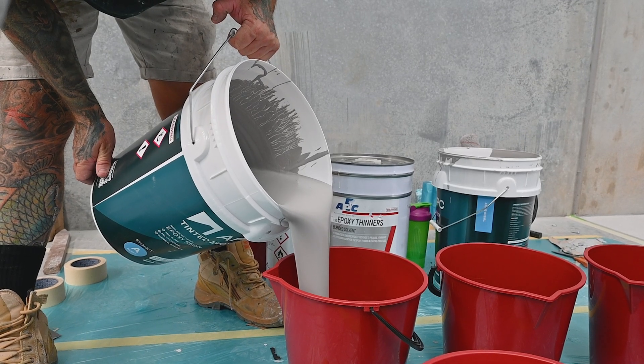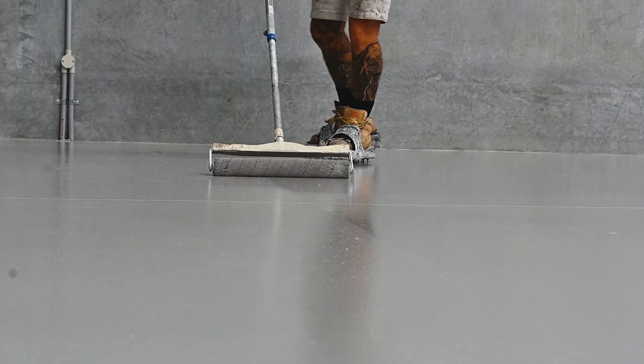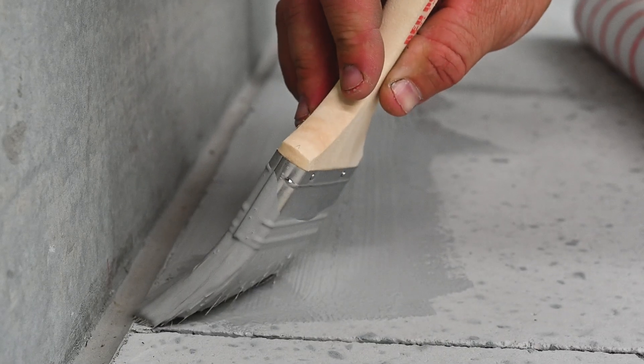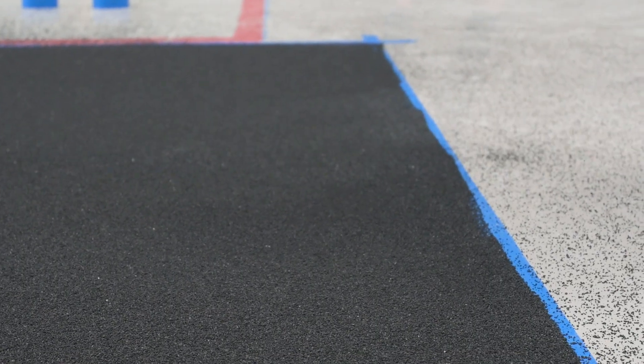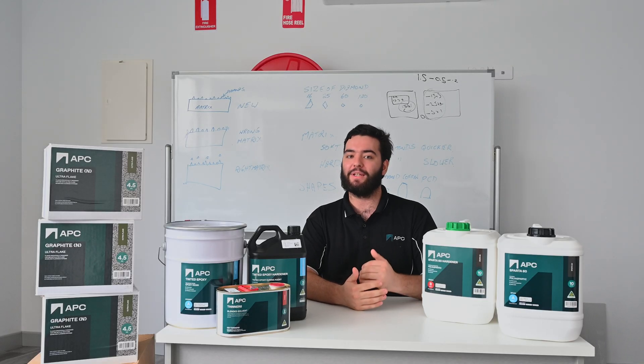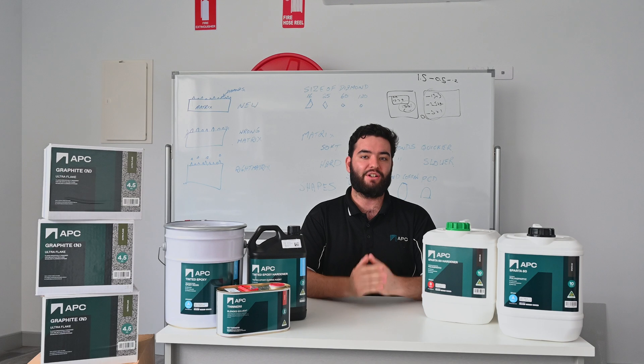These risks can be avoided by using our four-coat systems, which gives time for the product to penetrate into the substrate for a stronger bond. All of our systems begin with a prime coat designed to ensure a strong bite to the concrete, followed by a base coat allowing for proper adhesion to the broadcast and bonding to the concrete. Depending on the system chosen, your flake or quartz distribution enhances the system's durability and aesthetic appeal, before finally being finished off with two UV top coats to seal the surface. By allowing each of the liquid layers to cure properly before applying the next, our multi-coat system significantly reduces the risk of adhesion issues and ensures a longer-lasting floor.